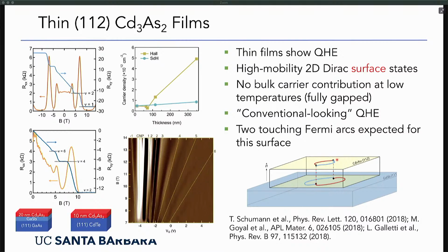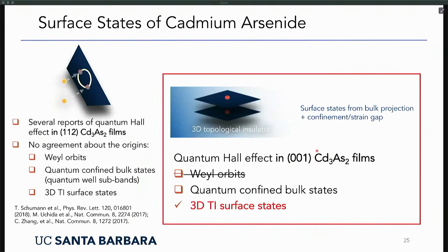These are probably from these Fermi arcs or Fermi loops, or residuals of those at least, that reside on these surfaces. Other groups, some of whom I've referenced here, also saw this quantum Hall effect in 112 cadmium arsenide, and there was not much agreement in the literature about the origin. One suggestion was that these are due to Weyl orbits, where the Fermi arcs connect the top and bottom surfaces through the bulk of the film. That's unlikely in our case because I just showed you the bulk is gapped out. Another suggestion was quantum confined bulk states, so subbands as you would find in a quantum well. Our interpretation is that these are topological surface states.